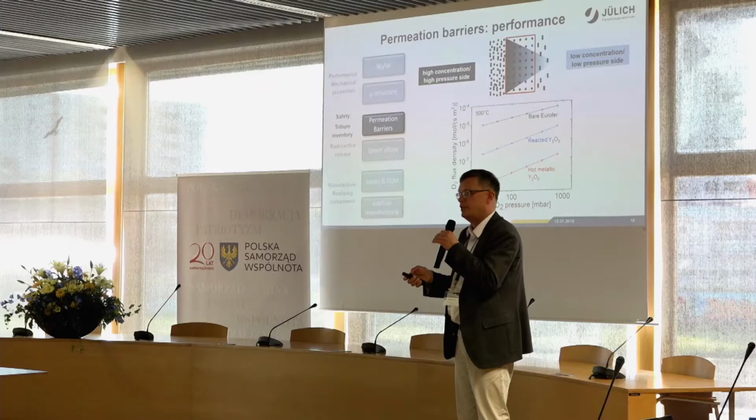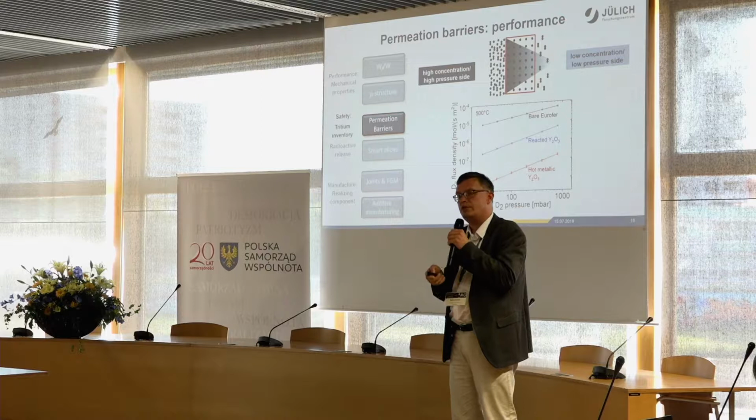Now, the question is about this tritium. It is bad if the tritium is accumulated in the structural components. However, from the safety point of view and licensing point of view, it is not as bad because we know where the tritium is. So the people want to have, let's say, the location. It becomes really bad if tritium goes to the cooling channel, providing all kinds of tritium-activated corrosion, starting to vaporize and going through micro leaks, which are essentially not detectable. So these barriers can be put at the interface of the cooling channels to have this passive defense.